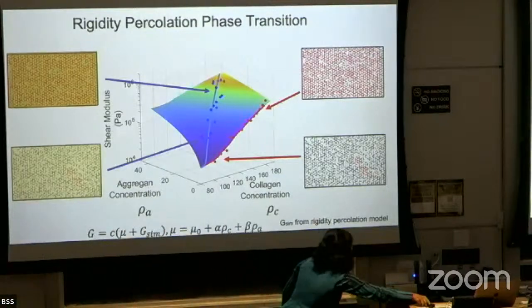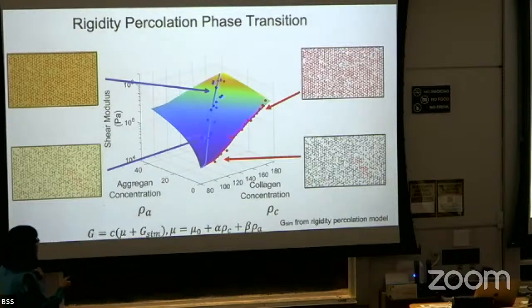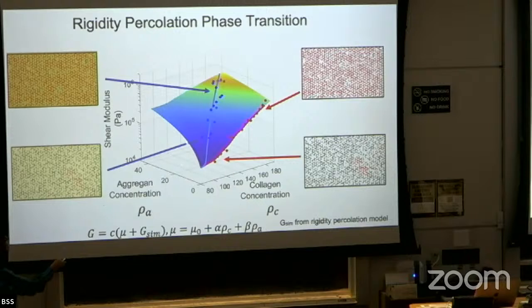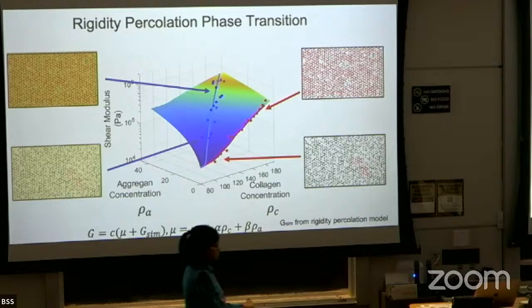Okay. So now with the assumptions in the picture that we do have, let's say you can look at a slice where you have very little collagen, no aggrecan, a lot of collagen, no aggrecan, a lot of collagen, a lot of aggrecan, a little bit of collagen, a lot of aggrecan. All these situations belong to different parts of the phase diagram, but you can look at any other combination of composition, and you can expand out. These solid lines are predictions of the theory when fitted to the experimental data, right? And these other parts are extrapolated versions of this theory.